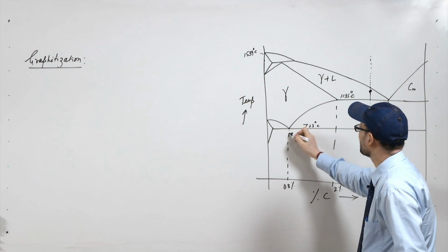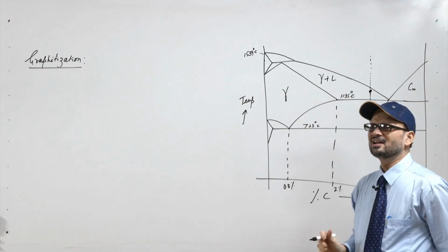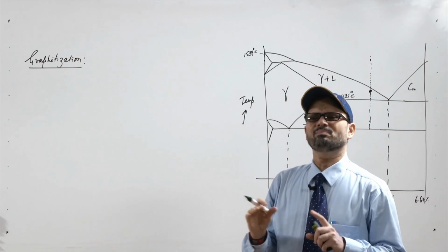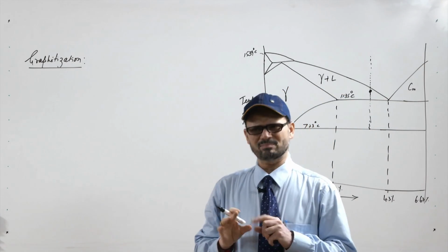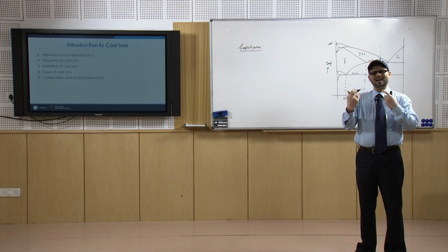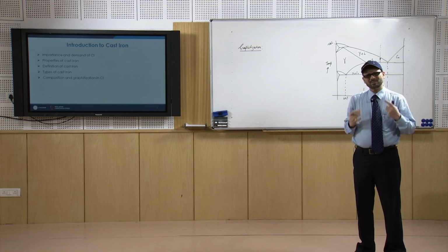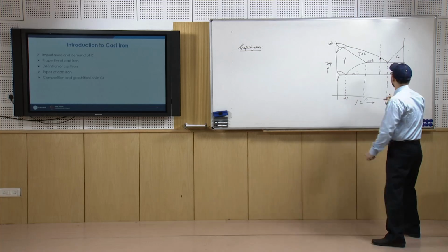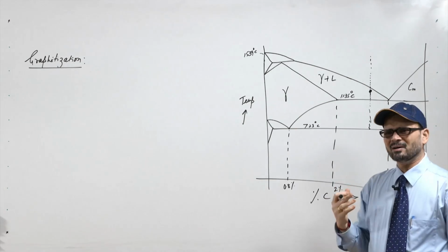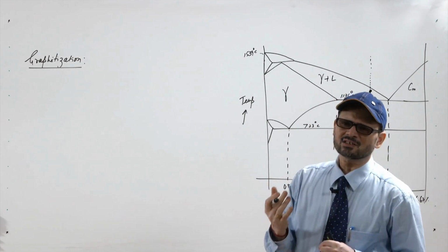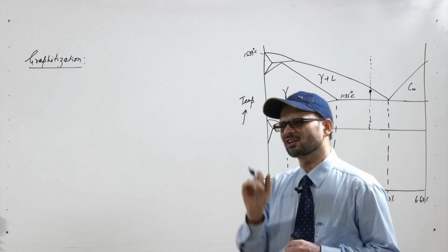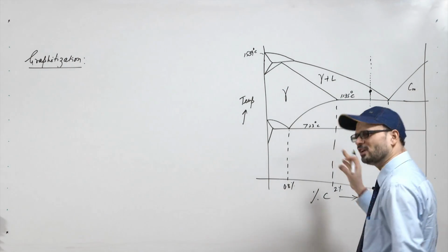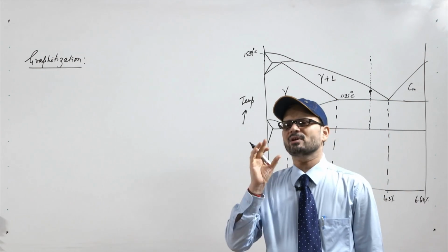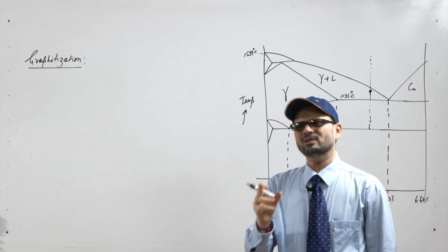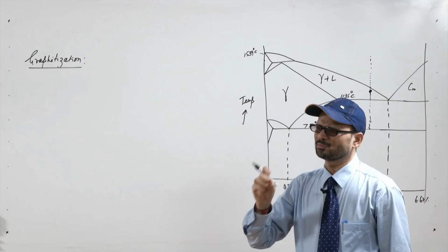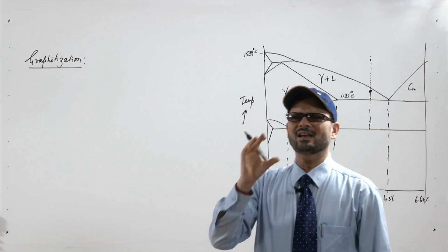So, you have this pearlitic structure, you have ferrite plus pearlite. So, the matrix may be ferrite or pearlite or a combination of ferrite and pearlite. Now, what type of matrix you will get depends upon the extent of graphitization. If the graphitization is maximum, then you are likely to get the ferritic type of matrix, because most of the carbon which is released is present in the form of graphite because of the graphitization process and because of the presence of alloying elements like silicon.